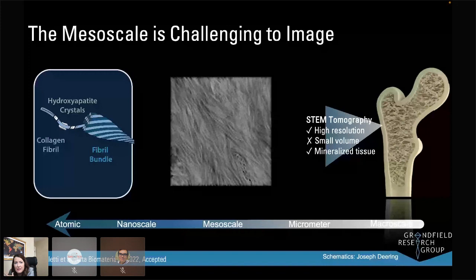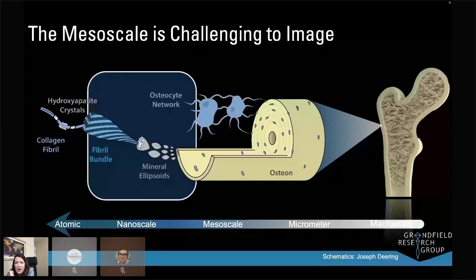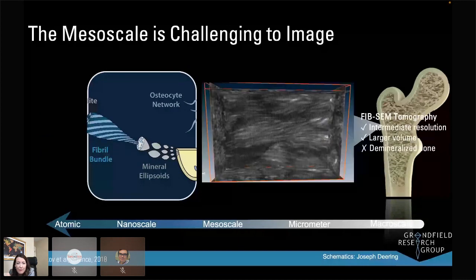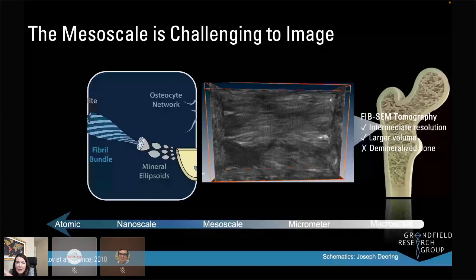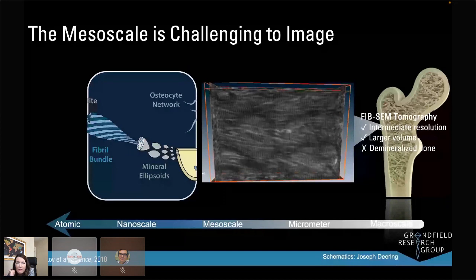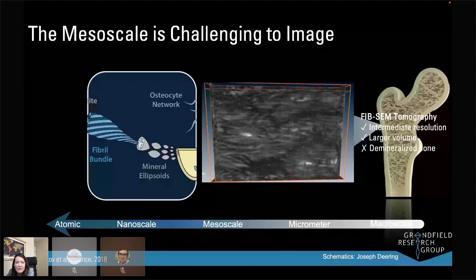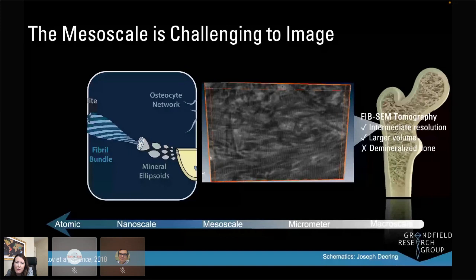To look at a little bit larger networks, focused ion beam is one of the tools you can use. Instead of using it to prepare samples for the TEM, it can be used in a 3D imaging mode. This is an example of work done by Natalie Reznikov, and here you can see collagen banding really clearly. So you have a slightly larger volume, tens of microns, with intermediate resolution—quite good, the resolution of an SEM. This data set shown here is on demineralized bone, so it's missing the mineral component.